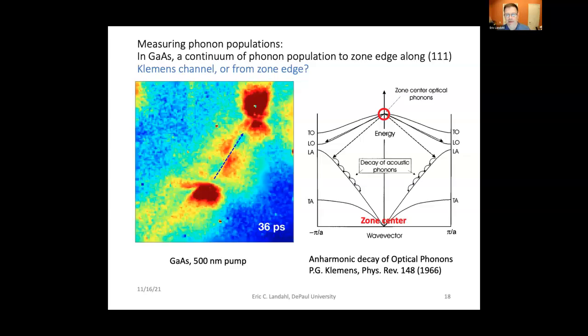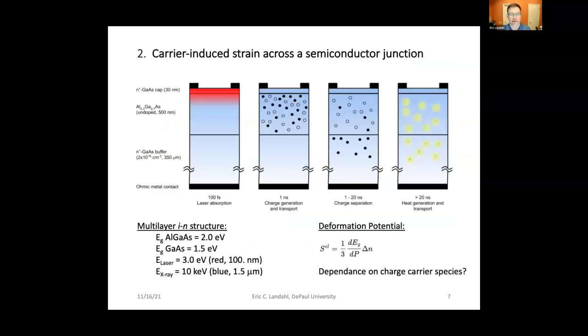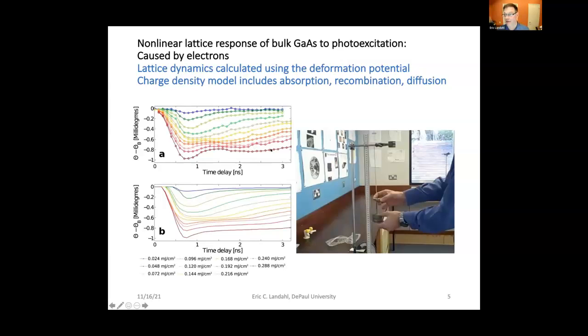So let me go back to those quickly at the beginning. You asked about why these long time scales and why it's a few nanoseconds. This is recombination and diffusion time, of course, but we have frozen in what happened to the lattice. The lattice only moves so fast. And so although recombination is certainly happening at this time, we're still seeing the effects of the electrons having been there, especially, of course, for the first nanosecond, because that's the speed of sound over that probe depth. So we're really seeing things moving out of the probe region at these early times. In terms of your 100 nanoseconds, the gallium arsenide is heated after 100 nanoseconds, or not?